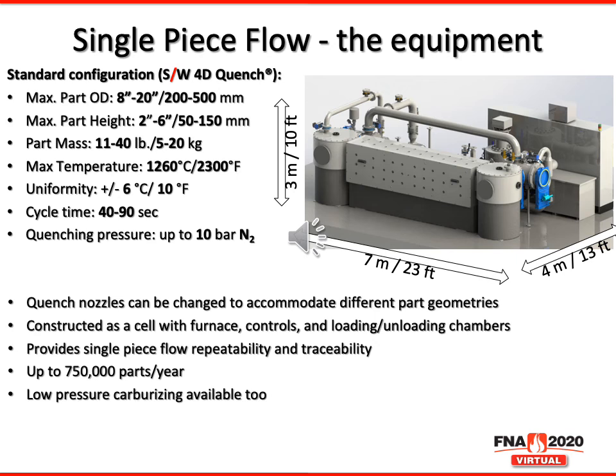This particular piece of equipment would have the maximum processing temperature of 2300 degrees Fahrenheit with a plus or minus 10 degree Fahrenheit uniformity, and using a cycle time of roughly up to 90 seconds, but depending on the part can go down as low as 40, can achieve a throughput of almost 750,000 parts a year. And of course, it has the same quenching capability we've been discussing of up to 10 bar in nitrogen.